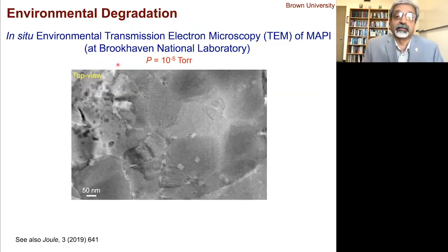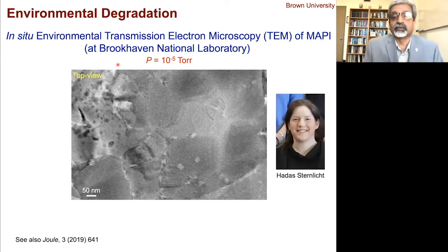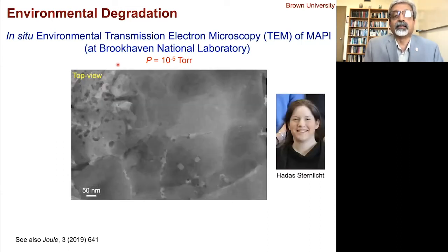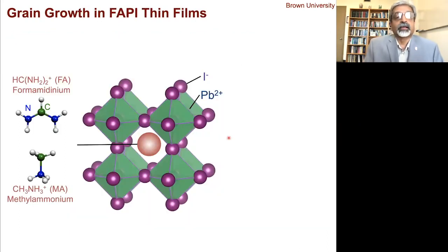So here's an in situ transmission electron microscopy of a MAPI film. This is done at Brookhaven National Lab, which has very special transmission electron microscopes, and this is the work of my postdoc, Hadas Sternlicht. Basically you let air into the transmission electron microscope, and you start to see degradation, but the degradation sort of decorates the grain boundaries. So it's preferentially attacking the grain boundaries. So if you increase the grain size or decrease the grain boundary density, then you'll make this material more stable.